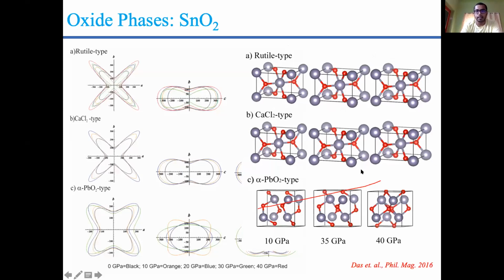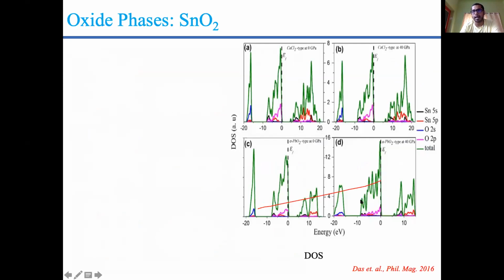Later, I calculated the density of states again at ambient and high pressure. Here you can see the multi-peak structure of alpha PbO2 type at 40 GPa, which is missing in CaCl2 type. So this multi-peak structure denotes the planar structure.